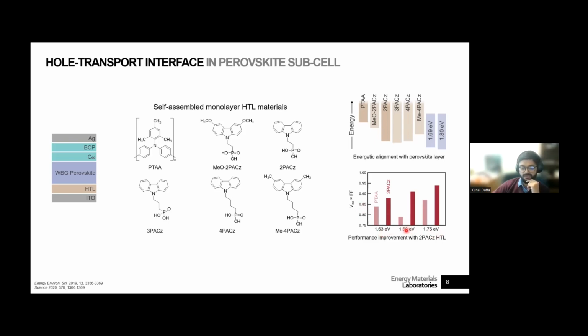So this one is for tandems. This can also be used for tandems if you can get the optics right. But across all band gaps, you get a better product of the VOC and the fill factor when you use 2PACz compared to when you use PTAA. So it was quite evident, and that's also been seen by other labs, that this material is quite robust and can be used across a bunch of different compositions.